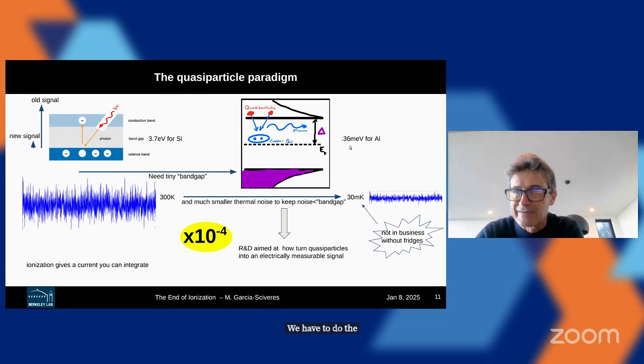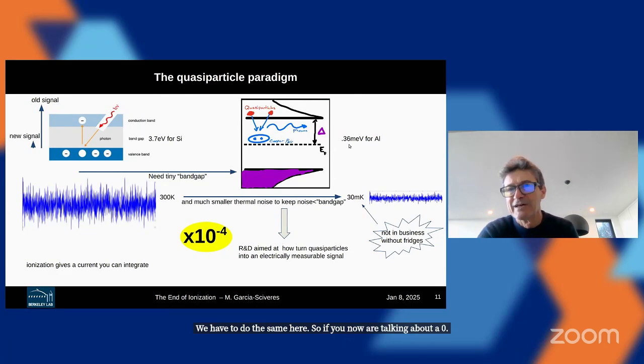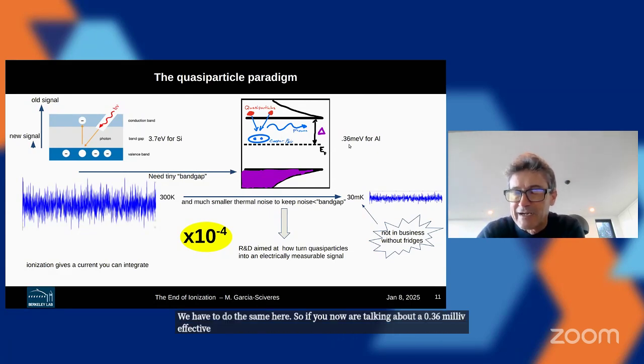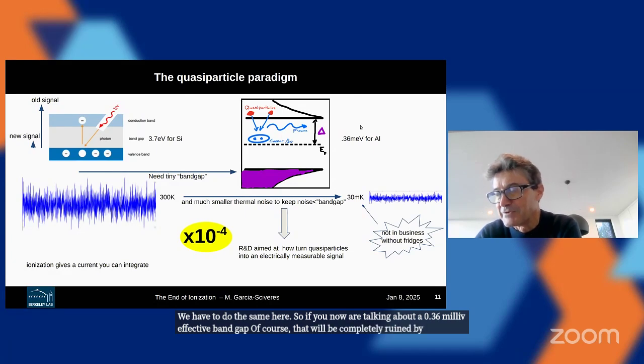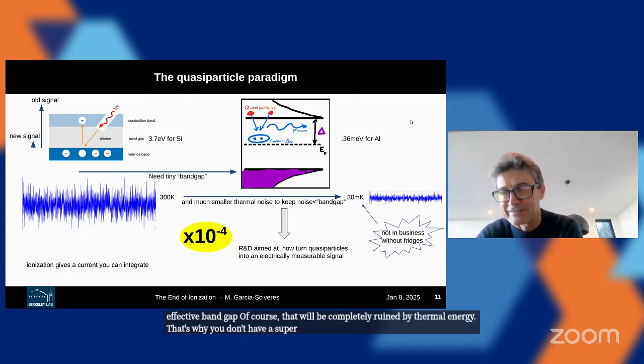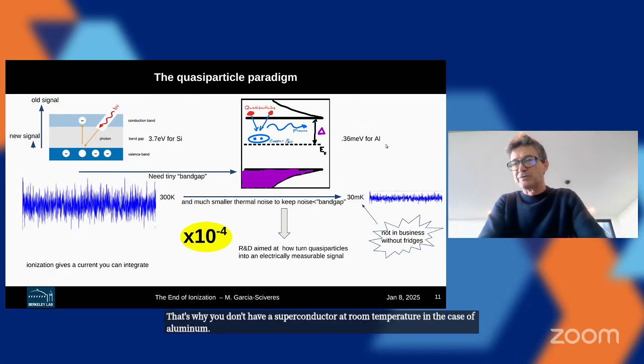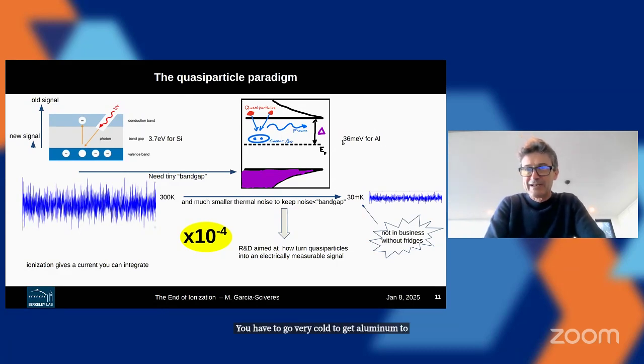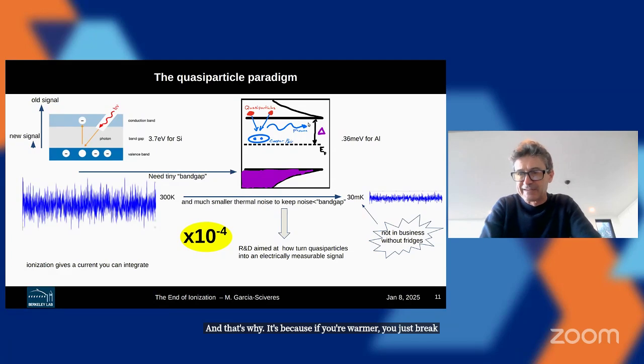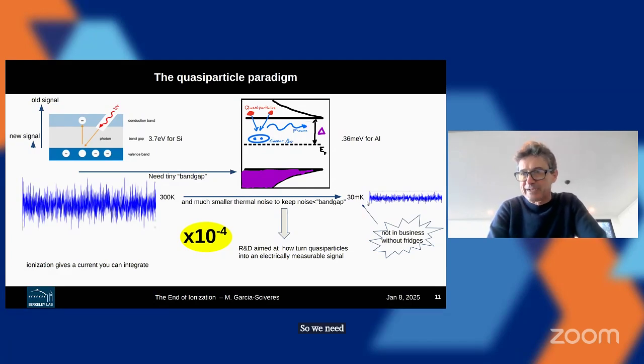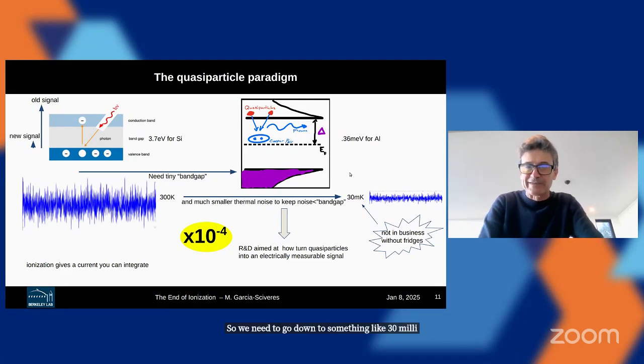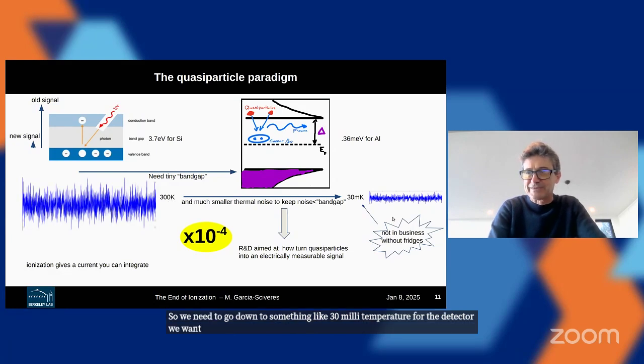So if you now are talking about a 0.36 milli eV effective band gap, of course, that will be completely ruined by thermal energy. That's why you don't have a superconductor at room temperature in the case of aluminum. You have to go very cold to get aluminum to superconduct. It's because if you're warmer, you just break all the Cooper pairs instantly. So we need to go down to something like 30 milli-K temperature for the detectors we want. Again, this is a factor of 10 to the 4, because you're reducing kT by 10 to the 4. You're reducing your band gap by 10 to the 4.